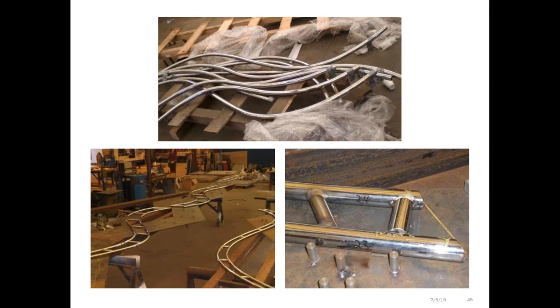The fabrication itself involved everything: machining, cold forming, welding. The basic material was round bar, which we ground to a mirror polish before we did anything to it in order to bring it back. One thing Gary did not talk about is that the material finishes quite well. It finishes and polishes as well, or a little bit better than the austenitic.